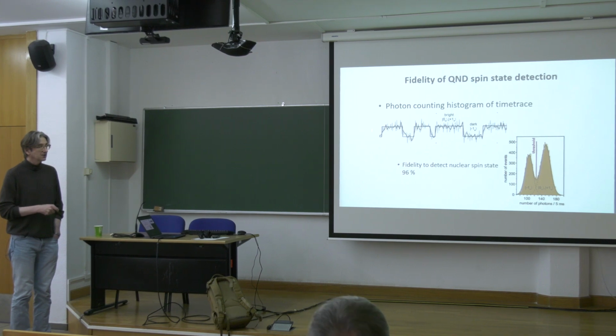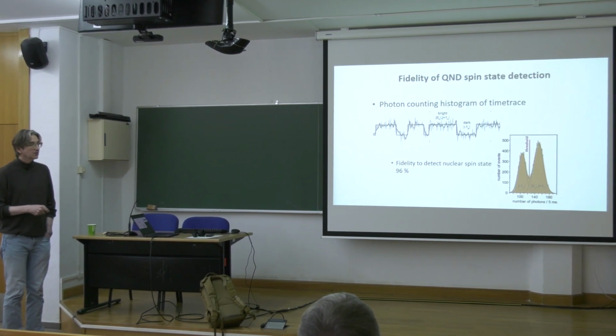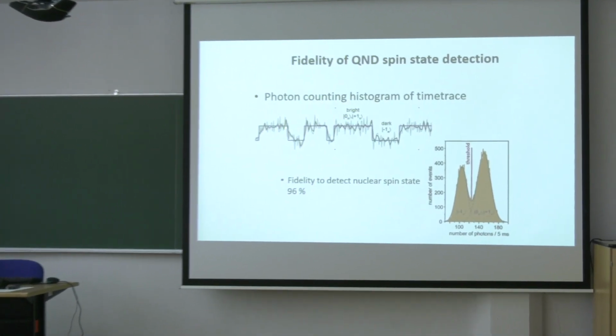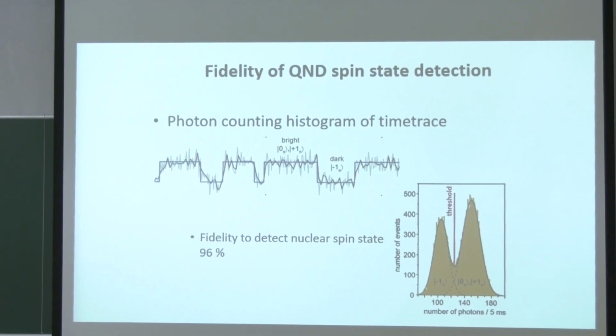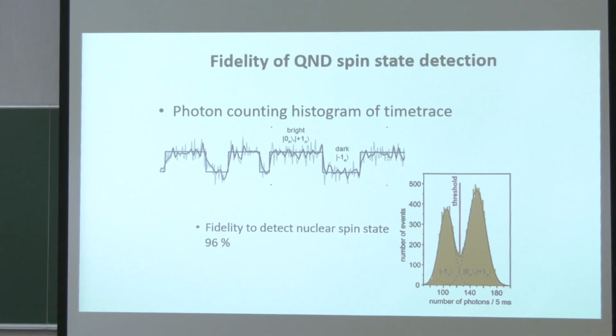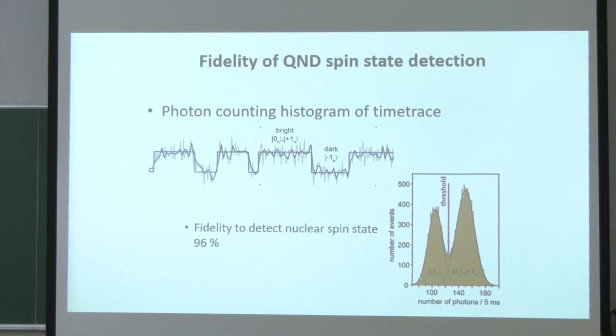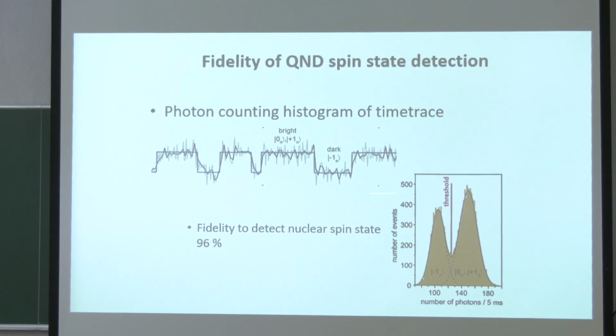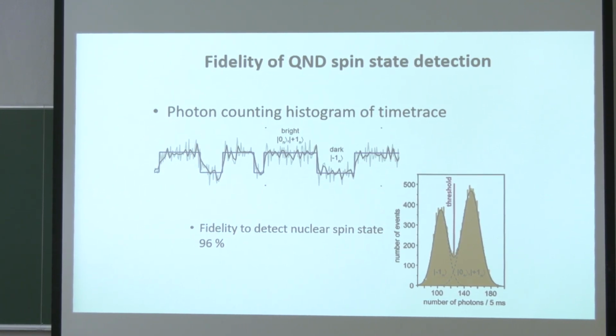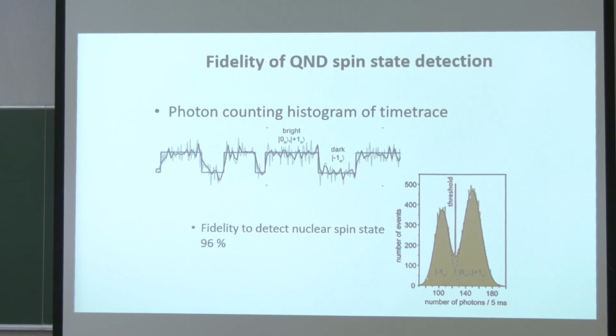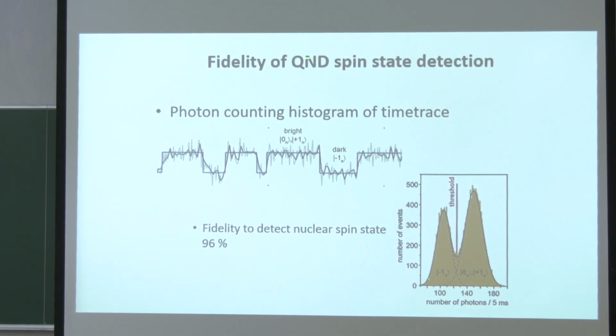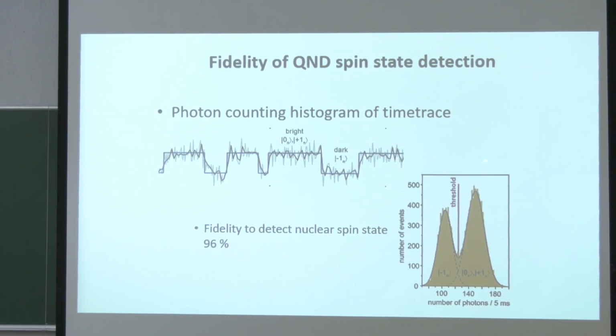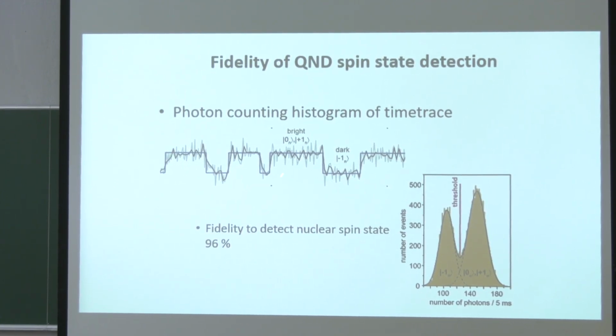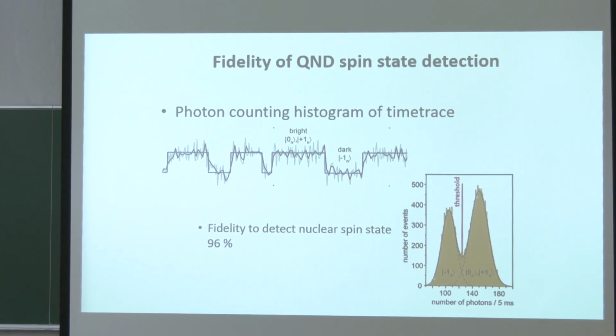What you see here is the fluorescence intensity versus time, measured for a single NV center. And what you see are jumps between bright and dark states. These jumps correspond to jumps of a single nuclear spin between spin up and spin down. The time scale here is about 1 second for the whole acquisition time. So that's very slow dynamics, and it allows you quantum non-demolition measurements of a single nuclear spin by measuring this intensity of fluorescence. Every time you measure a bright state here, it's nuclear spin up. If you have your NV center in a dark or darker state, then it's nuclear spin down.